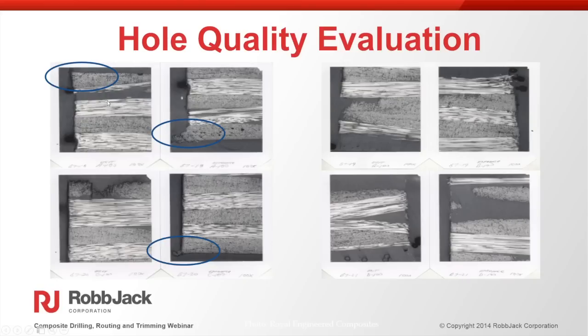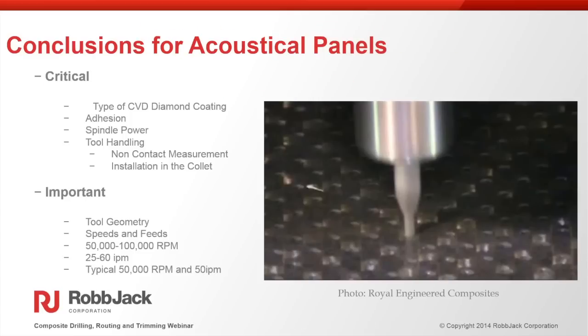And when we looked at the cross-section of these holes, you can see all the different kinds of problems that they ran into. You can see little cracks and delamination of the fibers in the circled area, areas where we have uncut fibers on the top edge. Here's another example of uncut fiber. We had fiber pull-out problems with different types of tools that we came up with.